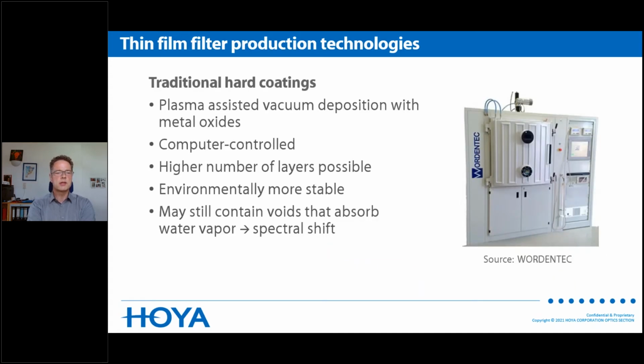Then later, the traditional hard coatings came into existence. They are produced with a plasma-assisted vacuum deposition process with metal oxides. Modern equipment is computer controlled, and you can deposit a higher number of layers for more complexity of the filter functionality. They are also environmentally more stable, but still may contain some voids that absorb water vapor. And with the water vapor, the refractive index changes, and so a spectral shift will occur. So you also need to consider that when looking at filters nowadays.